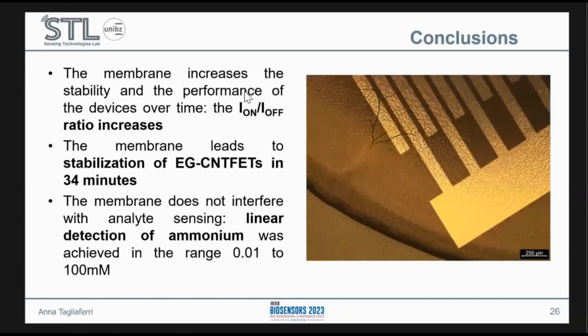To conclude very quickly, the membrane increases the stability and the performance of our devices, as indicated by the improvement in the on-off ratio. Also, the membrane leads to the effective stabilization of our devices in 34 minutes, improving much with respect to the state-of-the-art devices. And most importantly, the membrane does not interfere with the analyte sensing. We have successfully reached a linear detection of ammonium in the whole tested range.